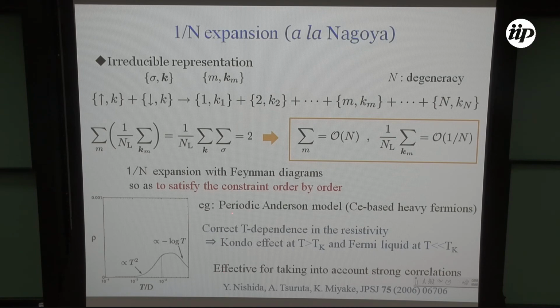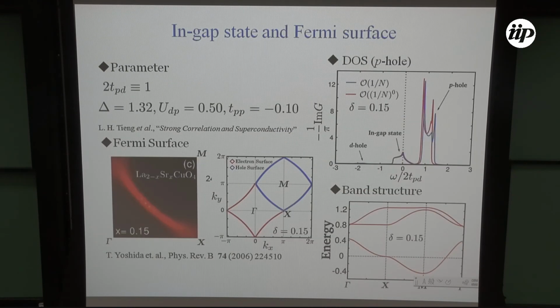For example, for the periodic Anderson model, we get the correct T dependence in the resistivity, namely Kondo-like behavior at T larger than Tk, and Fermi liquid at T less than Tk. These two limits are smoothly connected. So using this kind of technique, we calculated the parameters like this, and the Fermi surface corresponds to that of nearly LSCO. Also, the p holes have an in-gap state.